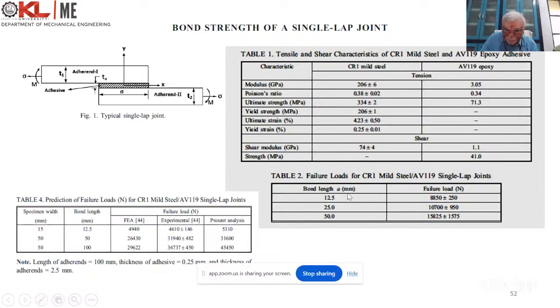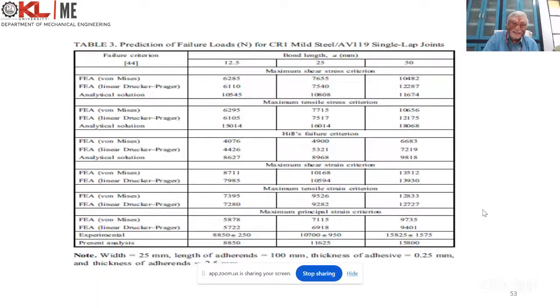Another one is that by varying the bond length, we measured the failure load. Different theories we applied, finite element analysis as well as analytical solution, whereas the point stress criteria we applied is closely matching with the test data. The point stress criteria assumes an inherent flaw, a defect. At that point, if you can accurately measure the stress, you will be in a position to identify at what load it will fail.